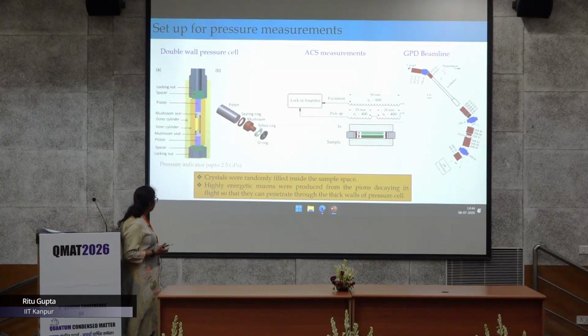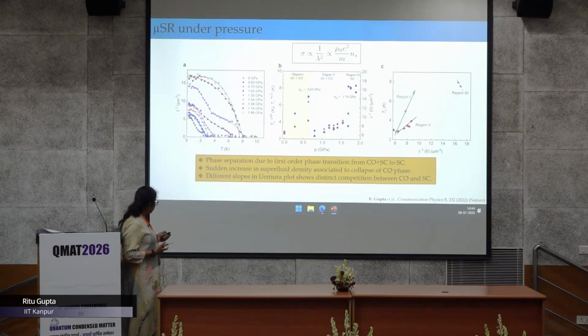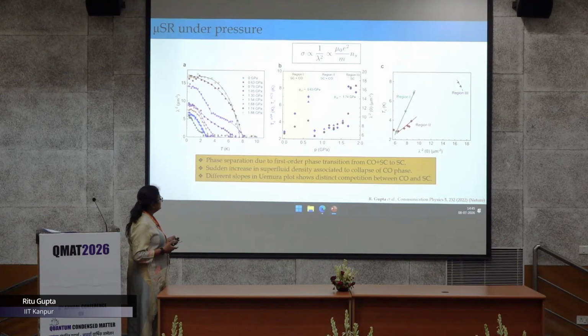So we again carried out different experiments, took different spectra at different temperatures and different pressures. So this is the summarized graph of inverse square magnetic penetration depth as a function of temperature. And we have also summarized the transition temperature values and the inverse square magnetic penetration depth, which is directly proportional to the superfluid density for a clean sample. So you can see the double dome like feature also in this superfluid density.